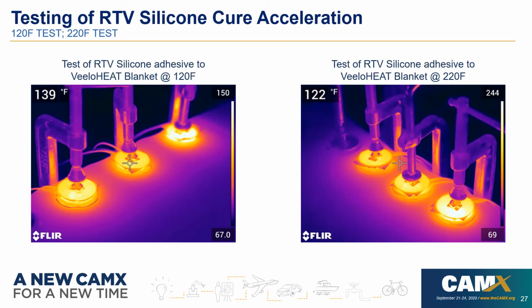Here you'll see some IR images of the blankets under test. On the left, we've got the 3 blankets at a 120 degree F hold, and on the right is a 220 degree hold. All the blankets appear to be relatively the same, pretty good uniformity. Happy with that. One of them does appear to be a little bit hotter. That must be due to the thermocouple placement within the internal of the blanket.